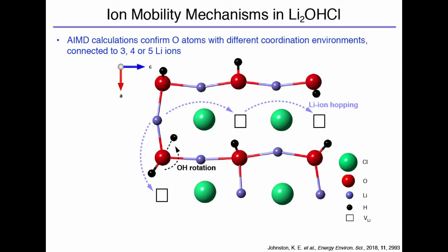And what we think is happening, based on calculation and experiment, is that the lithium ion will start to move or hop into vacant sites, for example, here. Now you'll notice that this OH group here is originally pointing towards this vacancy. Now as this lithium ion hops down into this vacancy and fills it, it then creates a vacancy there. What then happens to this OH group is it doesn't like being close to that lithium. It wants to have the maximum amount of space, because remember, it's going to try and rotate around a point. So the OH group undergoes a rotation and moves towards what's now the newly created vacancy.